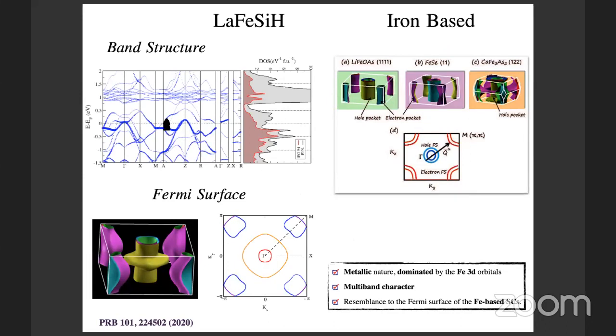So we also calculated the band structure using DFT theory. There are multiple bands crossing the Fermi level, and from the band structure, the main conclusion is that it's metallic in nature and dominated by the 3d orbitals. With this multiband character, the Fermi surface looks very similar to the iron-based superconductors, but the main difference is in this part. This part, the central belly part, is absent in iron-based superconductors.